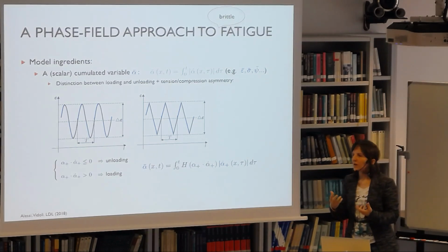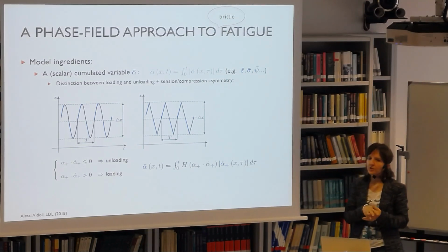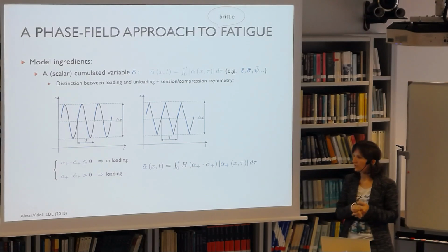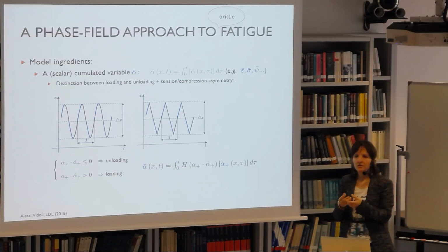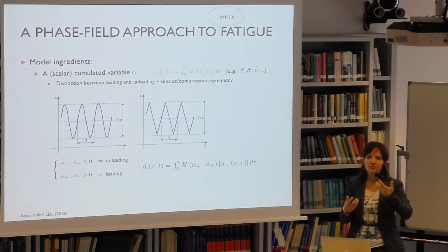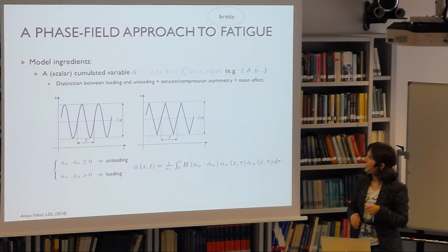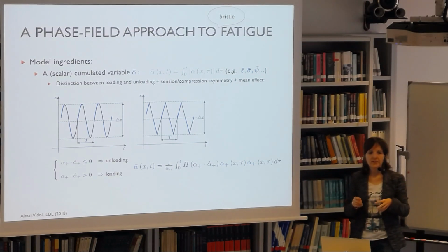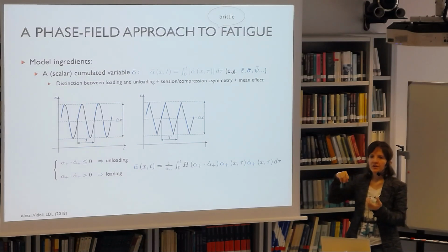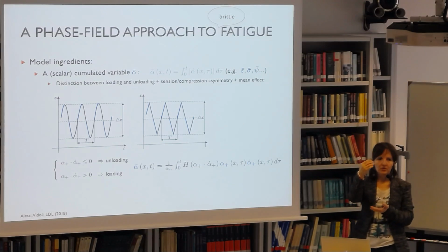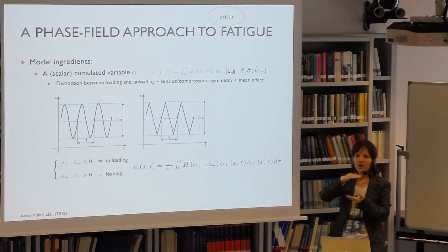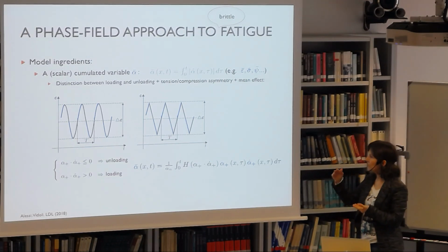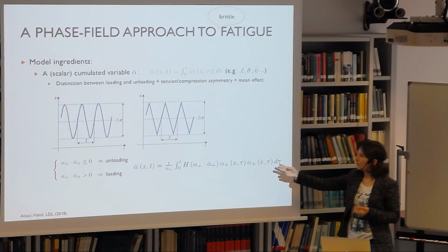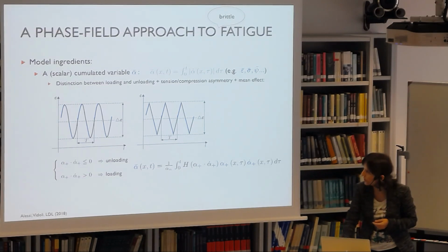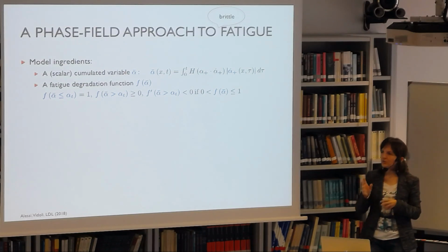So possibly you don't want to accumulate everything, you only want to accumulate the portion of the strains or stresses or elastic strain energy, depending on what you choose for accumulating variable, which you consider responsible for damage, consistently with what you use as split in your formulation. It can be a volumetric deviatoric split or any other type. So possibly you may also want to account for the so-called mean effect. It's known from experiments that if you have a given cycle, not only it's important how big the amplitude of this cycle is, but also how high the average value of the cycle is. And if you want to account for this, you need to introduce your alpha, not only the alpha dot in the integral. But this is, let's say, an option that we have not really used in our computations yet.